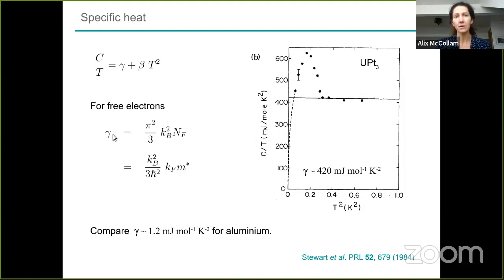For a free electron, the gamma coefficient is related to the effective mass in this way. So it's related to the density of states, and it's related to the effective mass in this way. So when you measure the de Haas van Alphen oscillations and measure the effective mass in the quantum oscillations, this should reflect the enhancement of the specific heat.